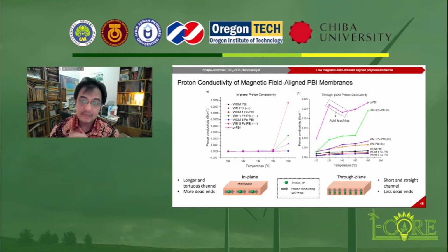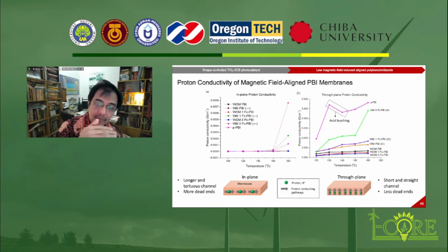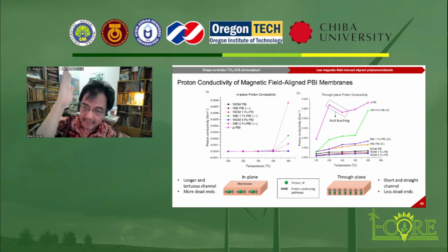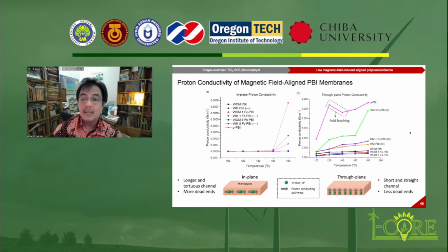Proton conductivity is one of the most important factors influencing membrane performance, especially in high temperature proton exchange membrane fuel cells. The proton conductivity of the polybenzimidazole based membranes was measured in the in plane direction and also the through plane direction at different temperatures, and we show it in this slide. Under the anhydrous condition, the proton conductivity increased with the increase of temperature. You can see here the conductivity increases from 100 to 180 degrees Celsius.